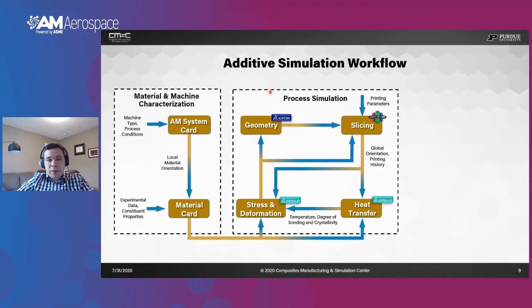So as part of the process simulation, basically it's a physics-based process simulation. We start with the geometry, then that is transferred into the slicer where we discretize that geometry into a set of layers and individual beads. Then as an outcome of the slicing, we get the machine code that is used for driving the system. In our case, the same G code is going to be used for driving a sequentially coupled thermomechanical analysis. So we first solve a heat transfer analysis to solve for the temperature, for the bonding between layers, for crystallinity in the case of printing with a semi-crystalline polymer, etc. And then we pass that into a stress and deformation analysis.